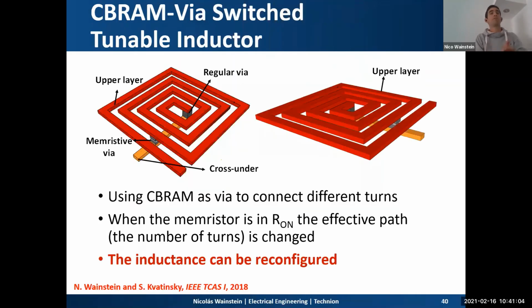It's ongoing work. Also, during my PhD, I explored how to use these switches to provide tunability to other back-end of the line devices, such as inductors. As you know, inductors are built in the top metal layers using spiral loops to exploit the mutual inductance between the wires. And the inner terminal is usually connected using a cross-under metal. Therefore, as in a memristive crossbar array, a memristive switch can be built in the cross junction between the upper layer and the cross-under. This is usually done in the top metal layers because we want a low resistance. This memristive via can be used to change the effective number of turns in the inductor.